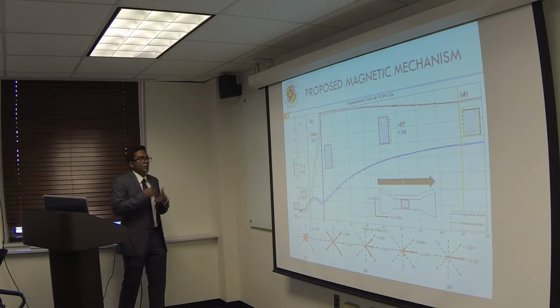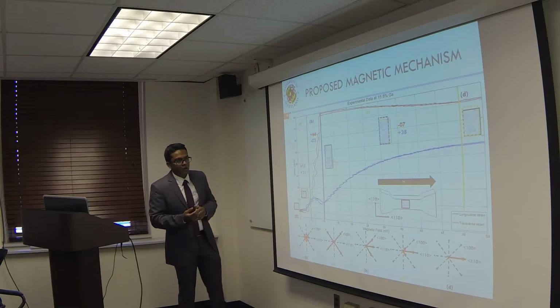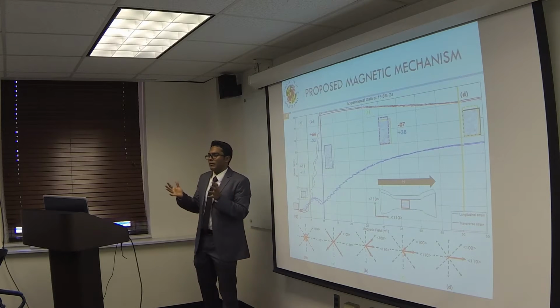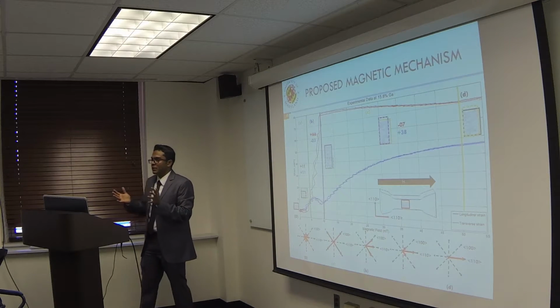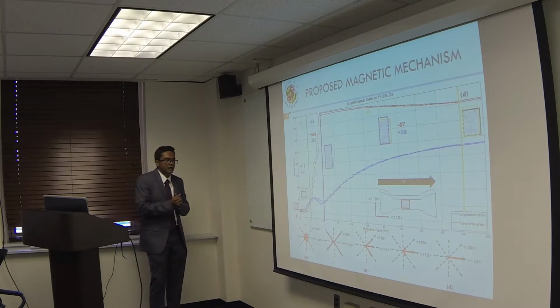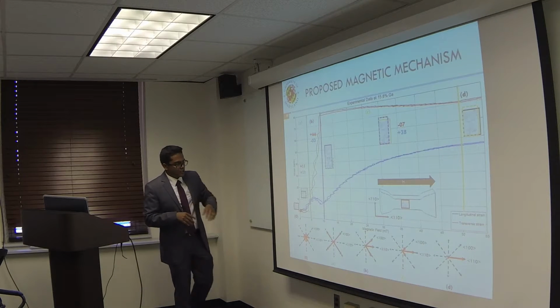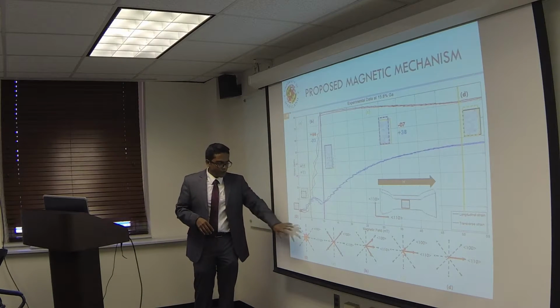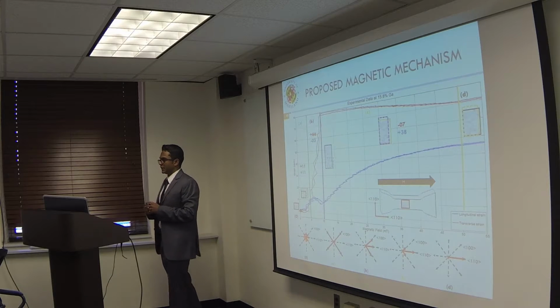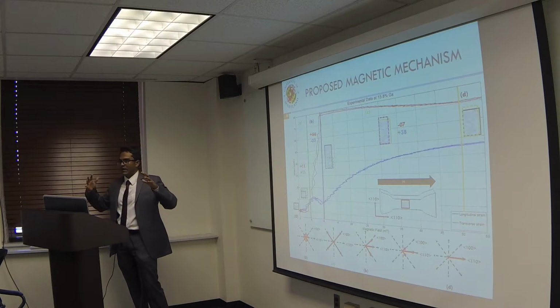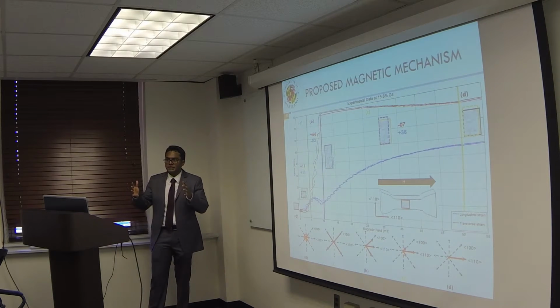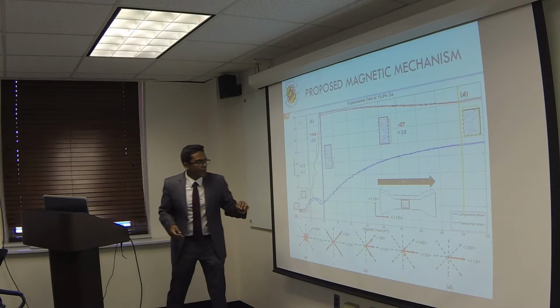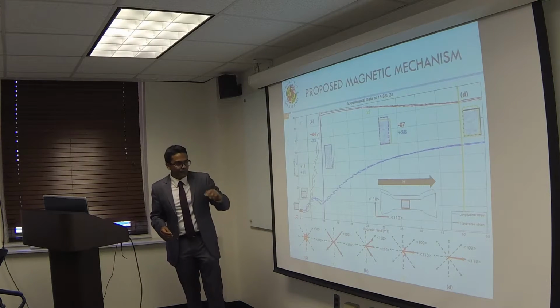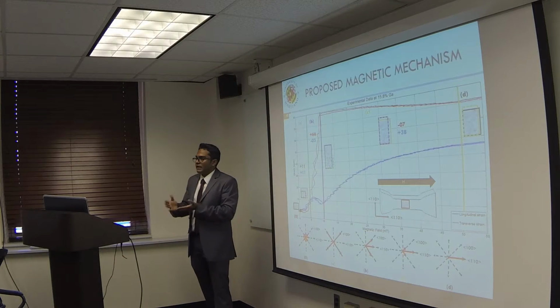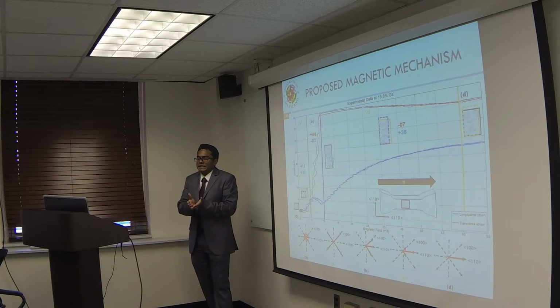So we decided to propose a magnetic model based on how the magnetic dipoles would interact with applied magnetic fields in Galfenol. We start at 0, and we assume a perfectly demagnetized state, so all the magnetic dipoles are randomly oriented such that the overall energy in the system is minimized. And when we start putting in energy, because of anisotropy, we know that the 100 direction is the easy direction.